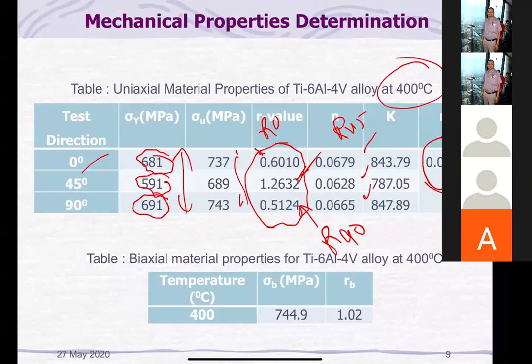M value is also very small, because the temperature is only 400 degrees centigrade. As Dr. Amit Bhattacharya was also saying, below 600 degrees centigrade, no microstructural changes are expected in this material. Oxide formation, or alpha beta converting into beta, these changes are not expected. Even phase changes are not possible below 745 or 800 degrees centigrade.